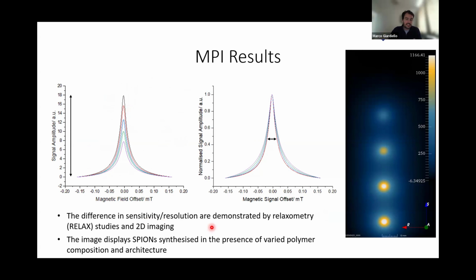We've not been able yet to do any in vivo with this, but we're about to start doing it. What is actually interesting is, although samples may have a lower MPI signal in an in vitro relaxometry study, they might accumulate differently because we're also able to adjust hydrodynamic diameter. So although the signal might be less, you can have the world's best MPI agent in a vial sat on your bench, but if it doesn't give a signal in the location you want it to be, then you don't have an agent. So although this one might be low here, it might have better accumulation. And that's what we're now about to start looking at with these samples.